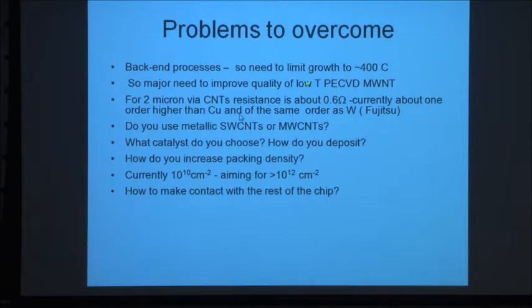You need to improve the quality of low temperature produced nanotubes. For instance, for a 2 micron via, the CNT resistance at present is about 0.6 ohms. That's about one order higher than copper. It's about the same order as tungsten.